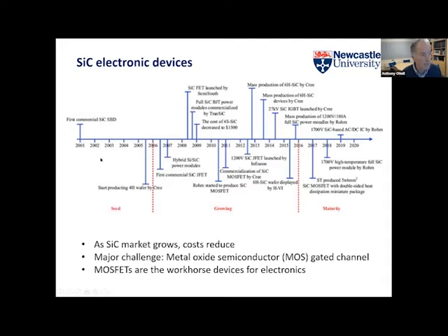As I say, back at around 2000, when I first started looking at this, the big problem was very poor mobility as an MOS interface, and I came back to it in 2015, 2016, and that was still a major problem. Compared with silicon, where you have electron mobilities in the region of a few hundred centimeters squared per volt second, in silicon carbide, those mobilities are down at around about 1 to 10 centimeters squared per volt second, so really quite poor.